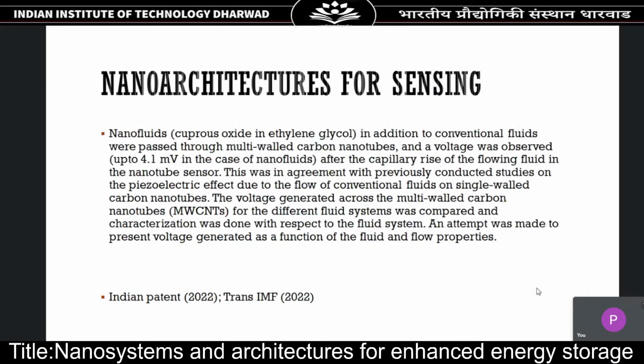And then I would like to talk a little bit about some of the nano architectures for sensing. This is in a way related to energy. It is not exactly supercapacitors, but I thought I could talk a little bit about this. We made a sensing device which has carbon nanotubes and nanofluids, and this was a flow device. We were able to get a very distinct voltage up to 4.1 millivolt, and this was due to the capillary rise of the fluid in the nanotube sensor.